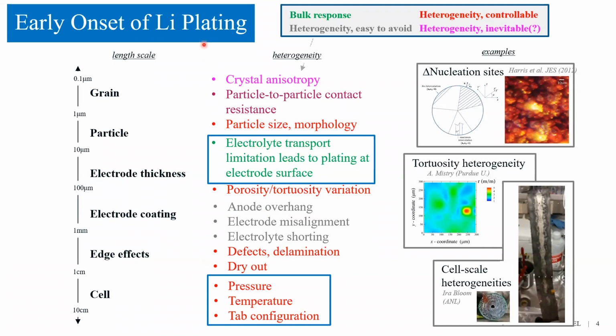Lithium plating is a formation of metallic lithium around the anode of a lithium battery during charging. It causes lithium battery to fail over time. Lithium plating is associated with heterogeneity. Heterogeneity leads to inhomogeneous distribution of lithium, resulting in stress that may cause lithium plating.